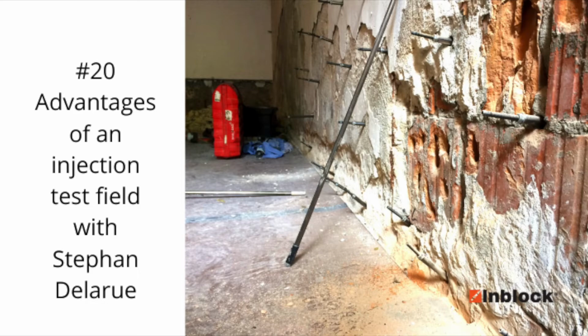Hole between two parts of the wall for insulation, for example, and therefore we do a lot of test injections. You can do that with the material, for example, on one hand, but it also depends on the structure or the target. I did it in the past on some spots with water, with colored water, for example, to find out, especially if you do a curtain injection,